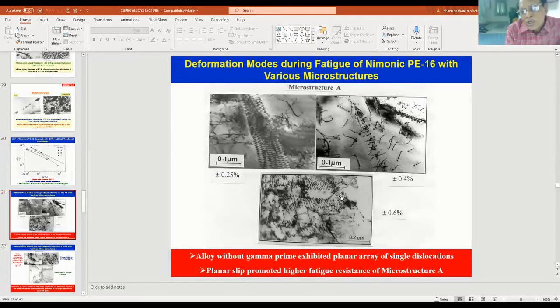In the solution annealed condition, you see that the dislocations are there in planar slip bands. Here, the number density of the slip bands varies as a function of strain amplitude. I have 0.25%, 0.4%, and 0.6%. The strain amplitude has increased. The dislocations are passing through in the planar slip bands like this. This is a desirable phenomenon. Planar slip, planar deformation in the matrix, gives you better fatigue resistance. That occurred in microstructure A, that is the solution annealed condition. But most importantly, you see that the dislocations are separate in the slip band.